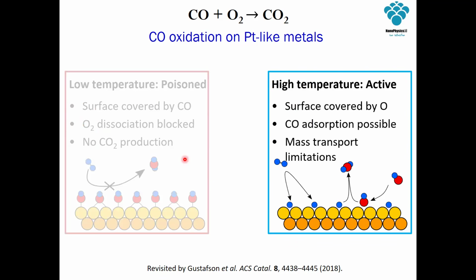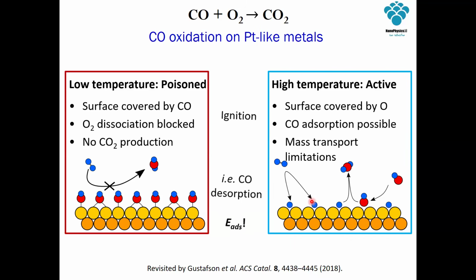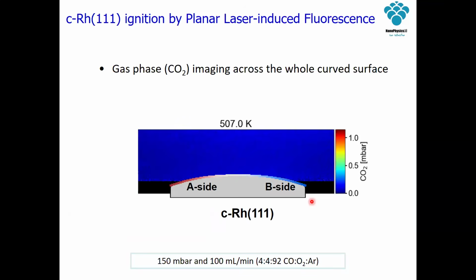If we go to the active part, we increase the temperature. Increasing temperature means that we are moving these atoms around. CO can desorb from the surface, and now we have space. Oxygen can split on the surface, can dissociate, and then we can do the process here. The difference between those is what we call the ignition, or when we start the catalytic process. And this is what we want to study here.